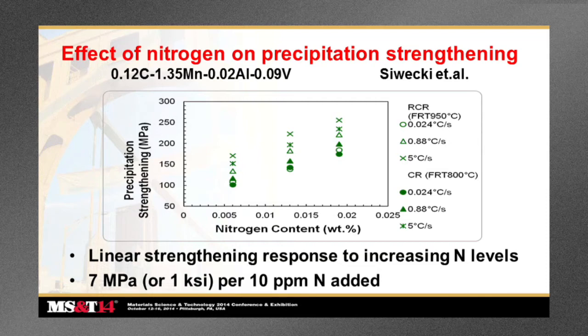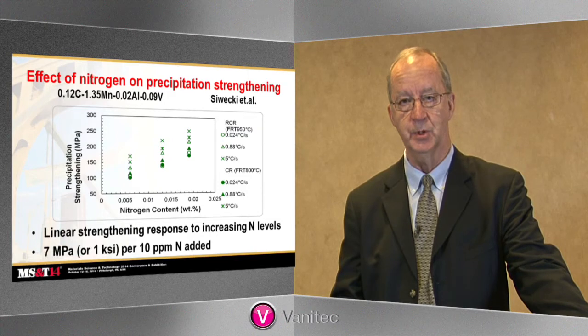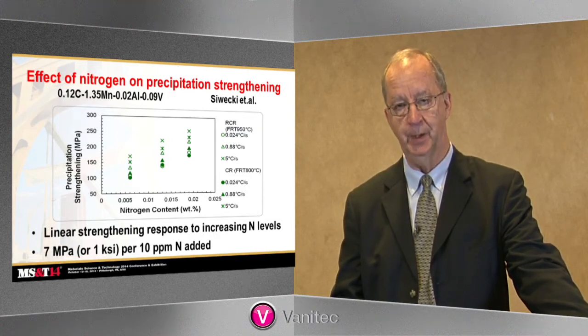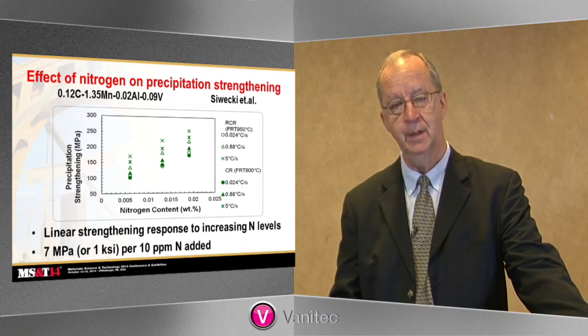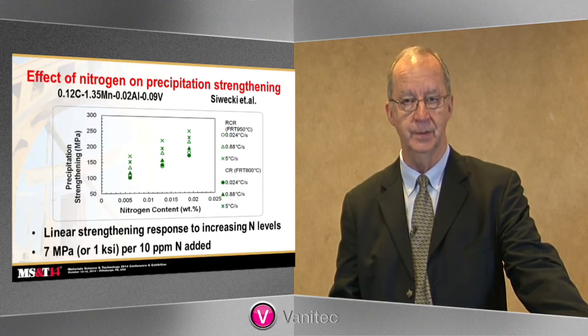which changed the absolute strength level, but the strengthening increase from the nitrogen contribution, as you can see, as we go from 50 to 120 to 180 region, that strengthening contribution was consistent across all of these processing and cooling rate conditions. And this rate of strengthening was about 7 megapascals, or 1 KSI in the inch-pound units, per 10 ppm nitrogen added. It turns out that this number has been repeated time and time again by multiple researchers and also many commercial applications of this alloy system, that this 7 megapascals increase in strength for 10 ppm nitrogen added, as long as it's substoichiometric to the vanadium nitrogen stoichiometric ratio.